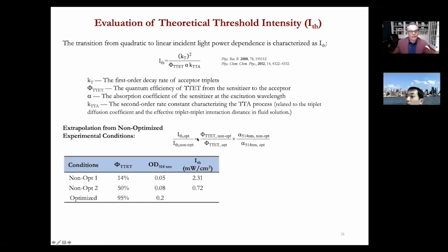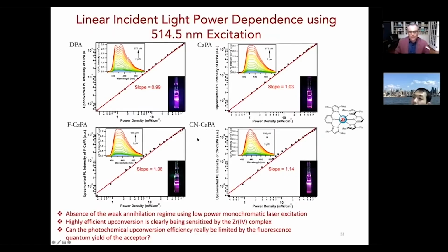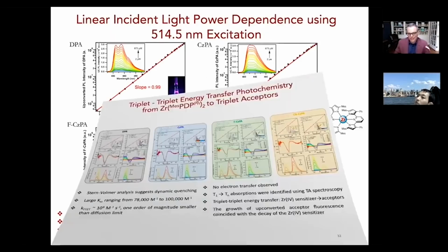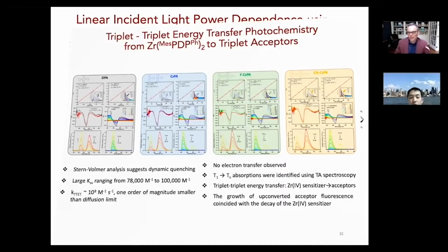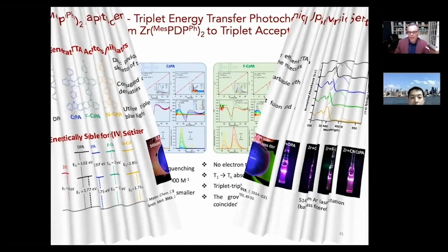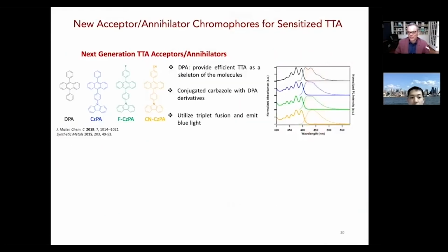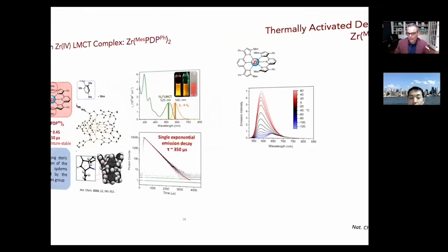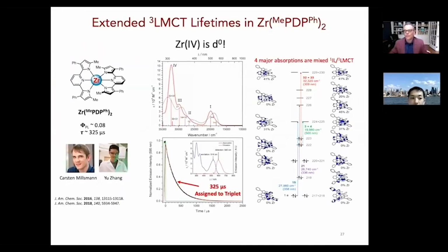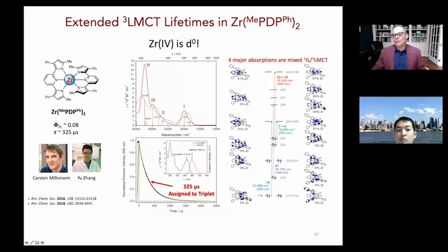Yeah, that's correct. It actually is a ligand to metal charge transfer, but it's not 100% ligand to metal charge transfer. I think it's 40% ligand to metal charge transfer and 60% ligand centered. These are calculations from Karsten. My group didn't do these. But if you look at the frontier transitions here, the transition here is 45% zirconium character. So zirconium is the acceptor orbital here.